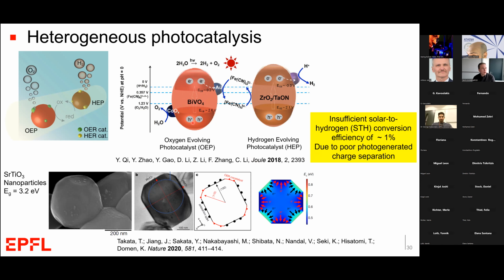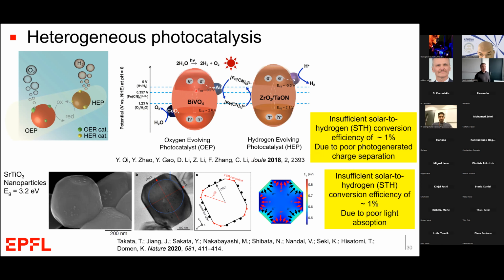In a typical photoelectrochemical cell or a photovoltaic cell, you're probably aware, we have some driving force for the charge separation, whether that be the use of electron extraction layers or a PN junction. And that's very difficult to implement on the nanoscale in a particle. Now, there has been some examples of that. For example, Domen's group in Japan has shown that these faceted strontium titanate nanoparticles have slightly different surface energies, which causes an electric field, which can actually effectively separate photogenerated electrons and holes in the nanoparticle itself. But a material like strontium titanate is quite high band gap. So again, the overall solar to hydrogen conversion efficiency is only about 1%.